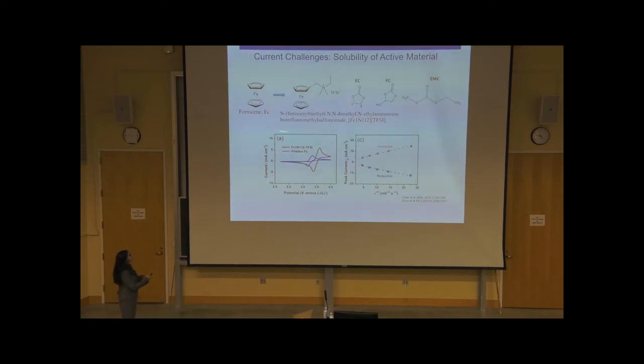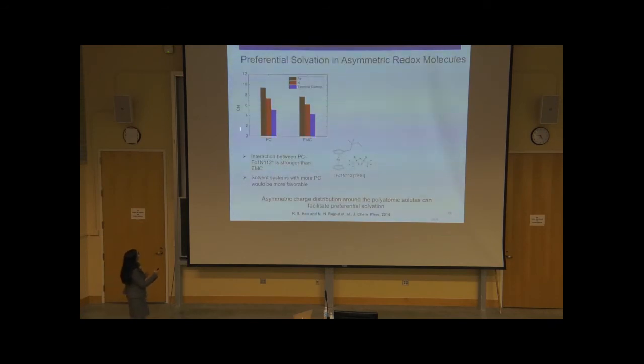So we tried to understand the solvation structure of this solution. And the first thing we observed is that propylene carbonate has a much higher coordination number around ferrocene as compared to EMC. So it has a preferential solvation around this ferrocene molecule compared to other solvents. So we thought that if we can increase the ratio of propylene carbonate in the solvent mixture, we might be able to increase the solubility.